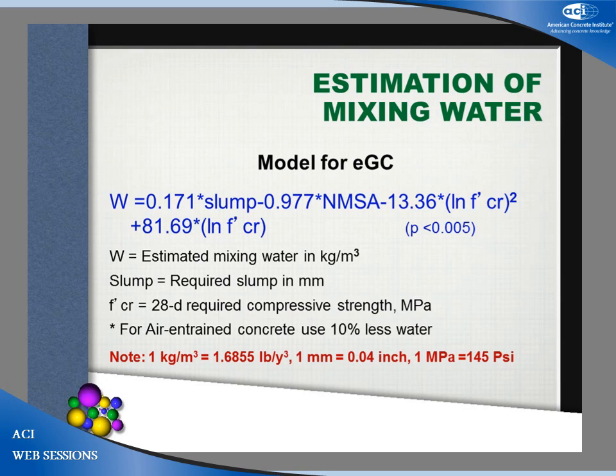We developed the statistical model for the estimation of the mixing water per unit volume of green concrete with three variables: slump, nominal maximum size of aggregate, and f'c, that is the required compressive strength. W is the estimated mixing water in kg per cubic meter, and that is for non-air-entrained concrete. If you are using air-entrained, just use 10% less water.